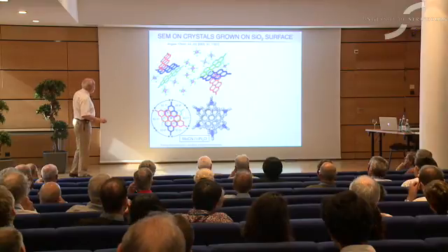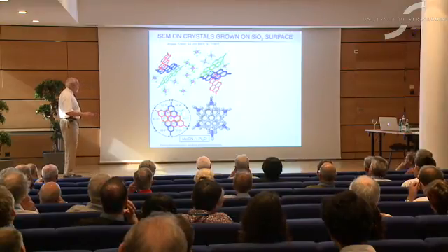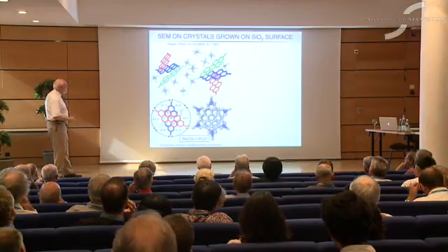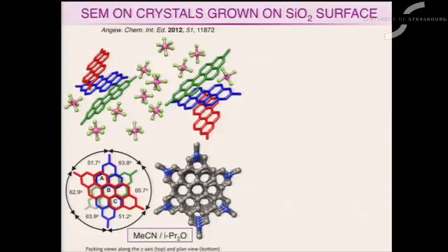And in looking at the crystal structure in more detail, these ABC repeats, which are in columns, the 3 of them, and the color picks this out, are differentiated, but they're related by a crystallographic inversion center, and are repeated ad nauseam, so that you get a very long column in each case, and in between you have, for this unit cell, the 12 counter ions that you would expect.